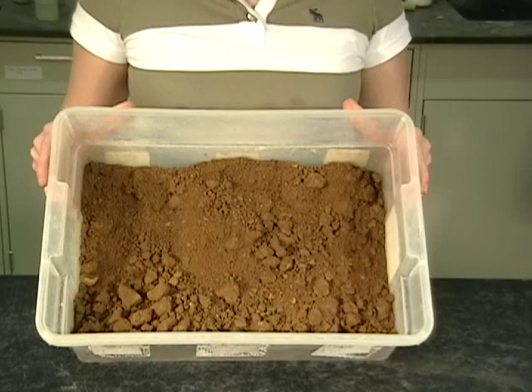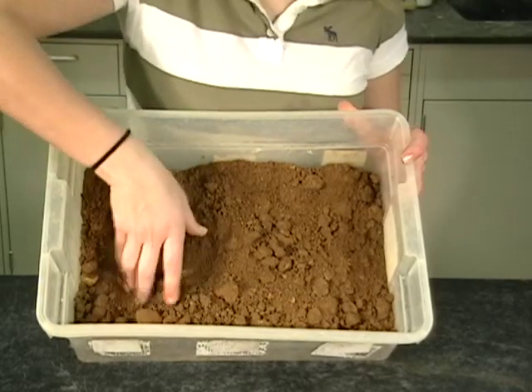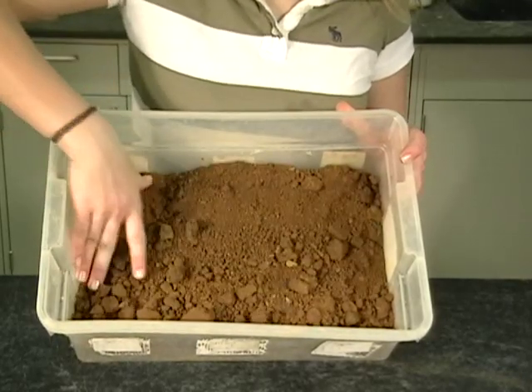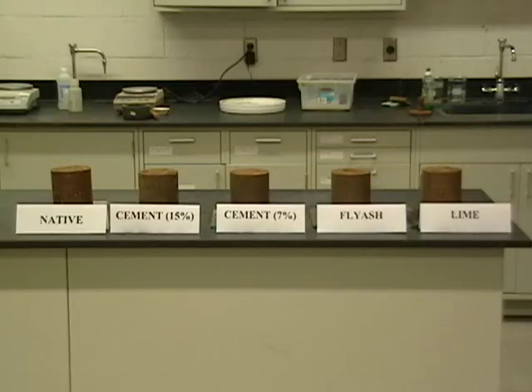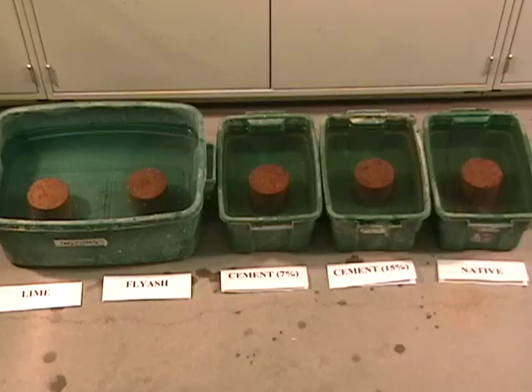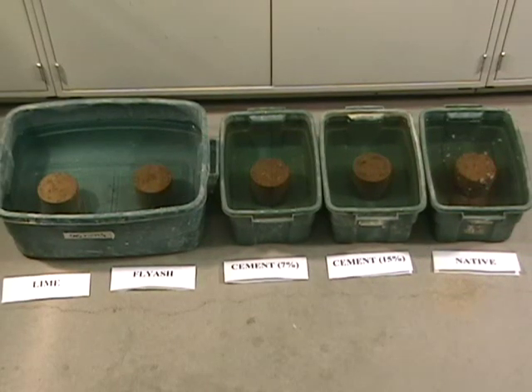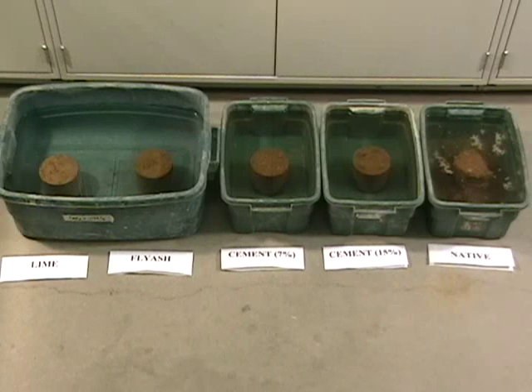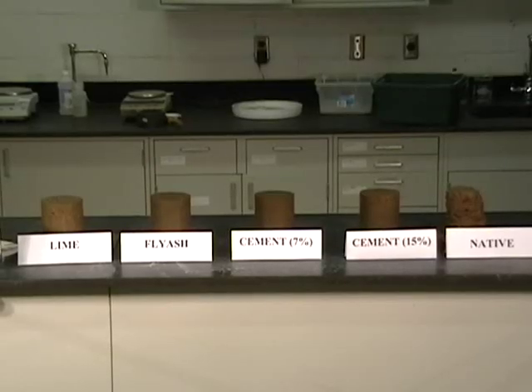A simple experiment illustrates the benefits of soil treatment. This soil was used to prepare samples mixed with lime, fly ash, two percentages of cement, and an untreated sample. Consider these treated samples cured for three days and then submerged. The native sample disintegrates over a period of several hours, while the lime, fly ash, and cement treated samples remain intact.